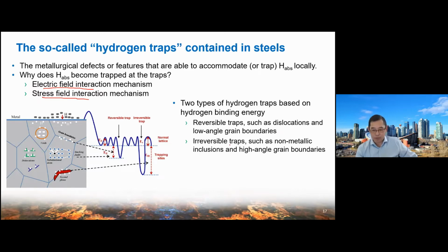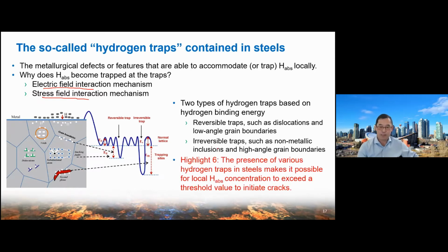Another type is irreversible. That means the hydrogen bonding energy is significant. When hydrogen is trapped in this location, it is not easy for hydrogen to leave this area. For example, non-metallic inclusions or high angle grain boundaries are irreversible traps. So hydrogen traps are very important, because different types of hydrogen traps in the steel can make the local hydrogen concentration exceed the threshold value, consequently causing the cracking event.